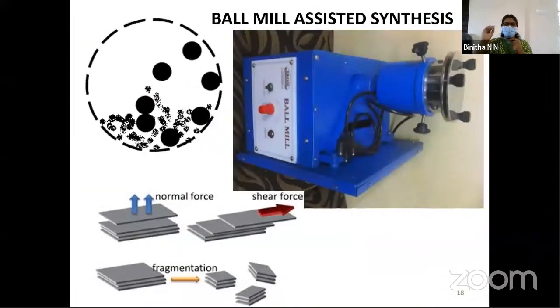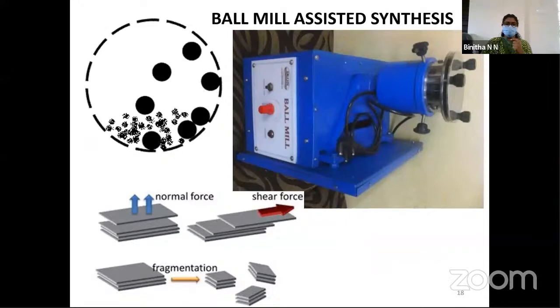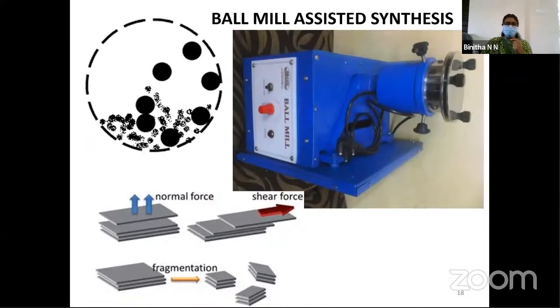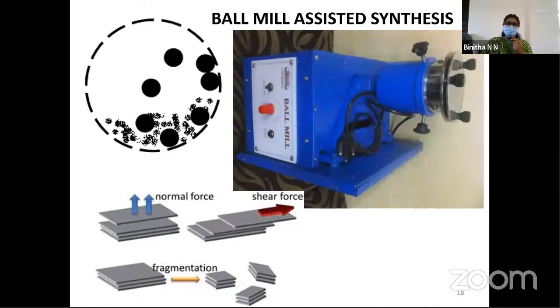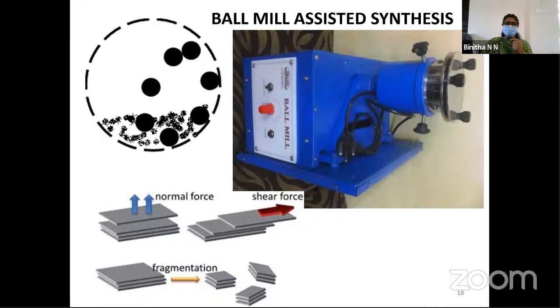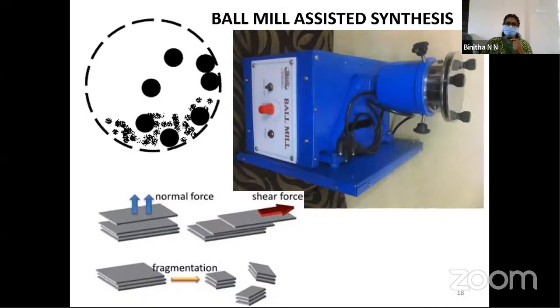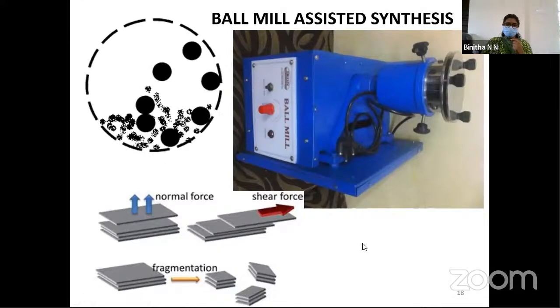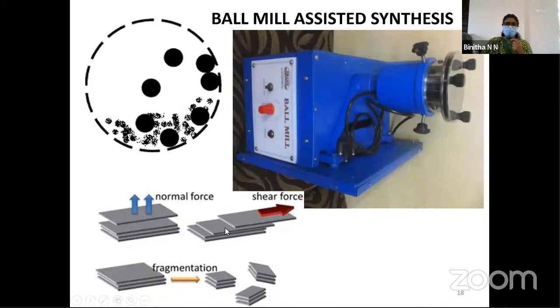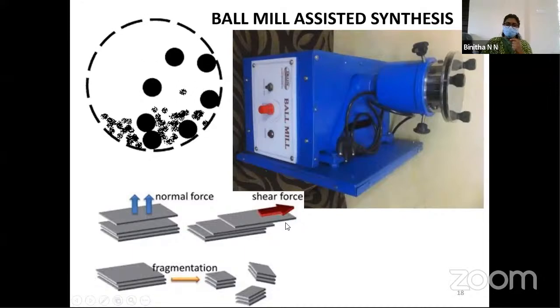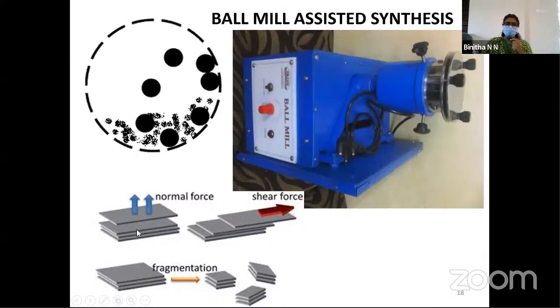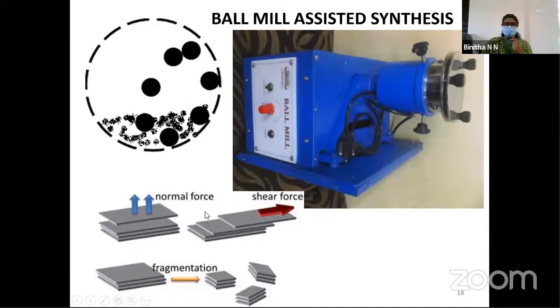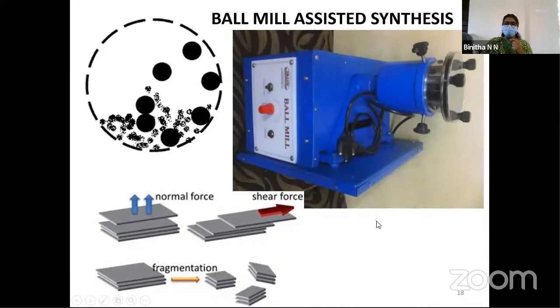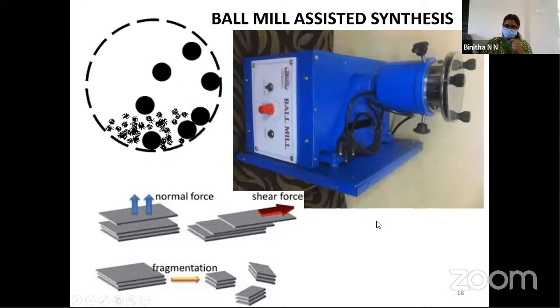In ball milling, graphite is subjected to balls. Milling occurs while rotating the medium. And if there are milling agents, they can assist the exfoliation of graphite. Graphite exfoliation can be done via shear force only. The action of normal force on graphite will lead to its fragmentation. So shear force dominated exfoliation only will lead to less defective graphene sheets.